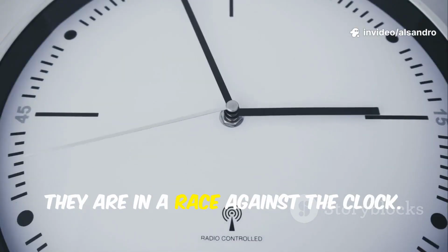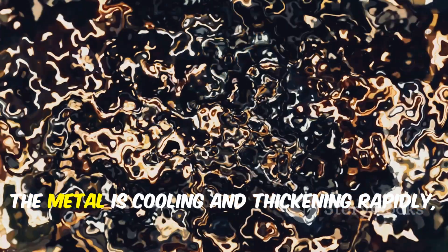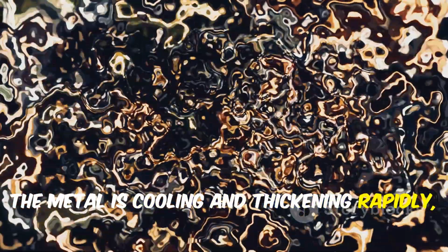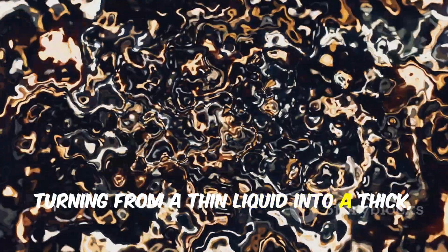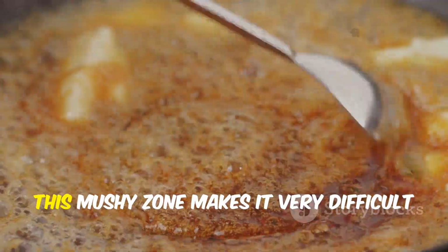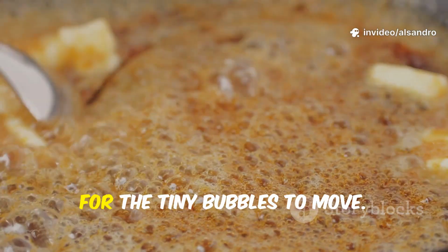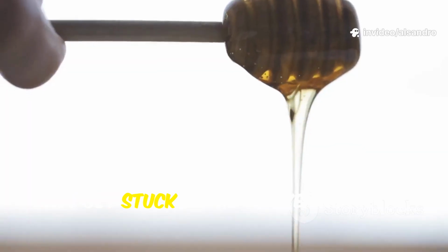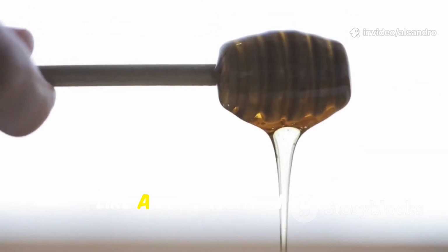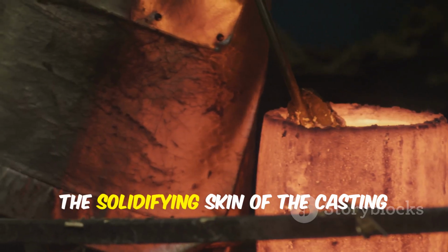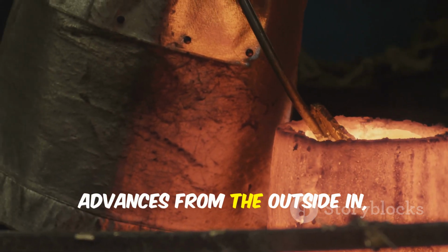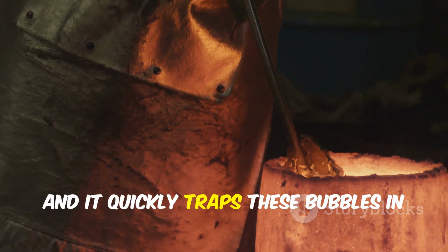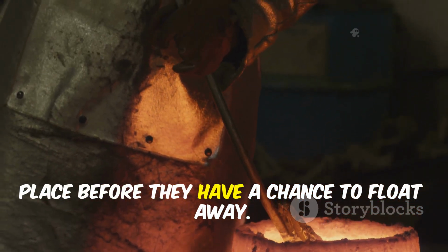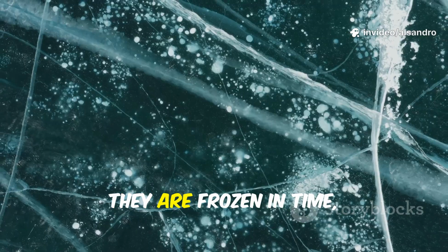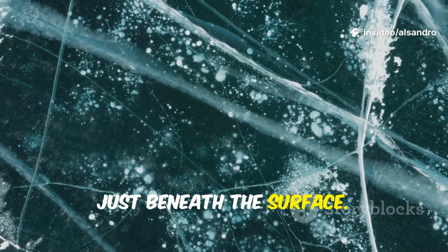However, they are in a race against the clock. The metal is cooling and thickening rapidly, turning from a thin liquid into a thick, syrupy slush. This mushy zone makes it very difficult for the tiny bubbles to move. They get stuck in the thickening metal like a fly caught in honey. The solidifying skin of the casting advances from the outside in, and it quickly traps these bubbles in place before they have a chance to float away. They are frozen in time, just beneath the surface.